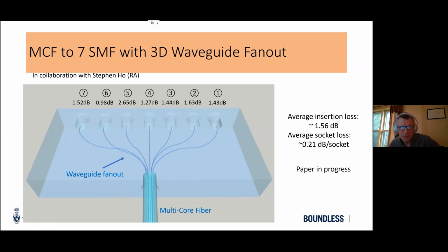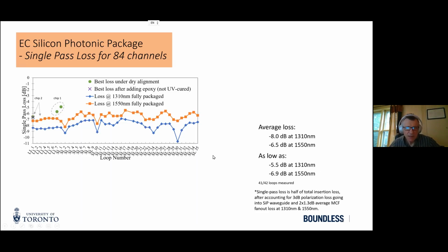And then we are testing the interposer losses. So with this alignment, we can comfortably get under 2 dB, well, except for this one, but we have bend losses and propagation losses with the laser formed waveguides. Most of these losses are due to misalignment of the actual fiber. It's not perfectly arranged waveguides. That's a commercial fiber.